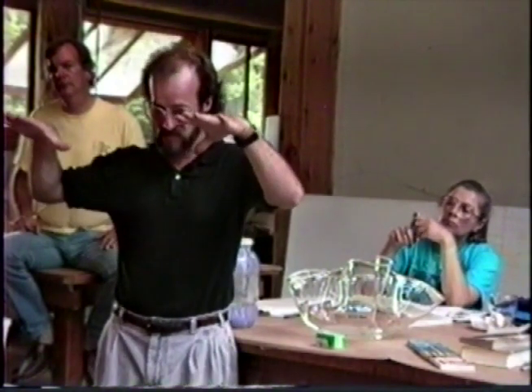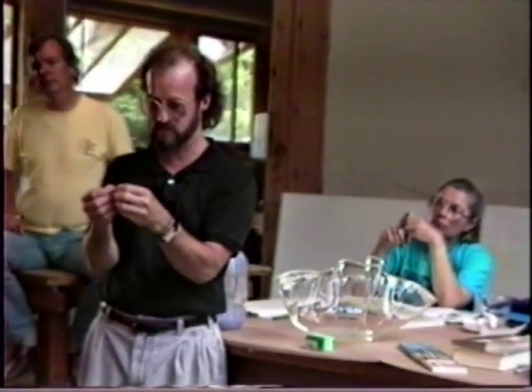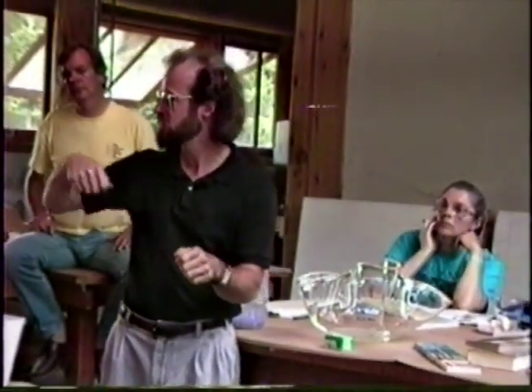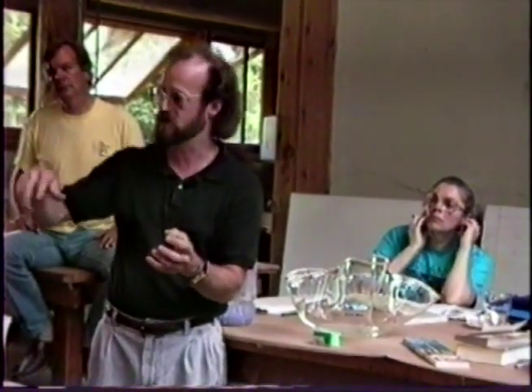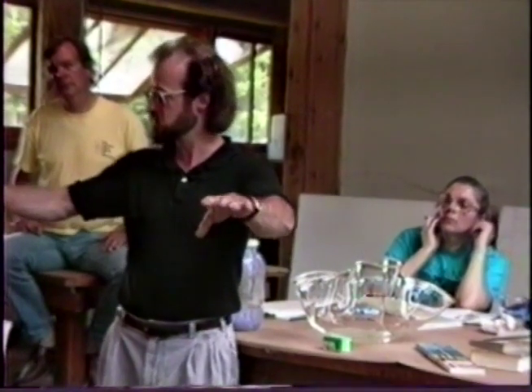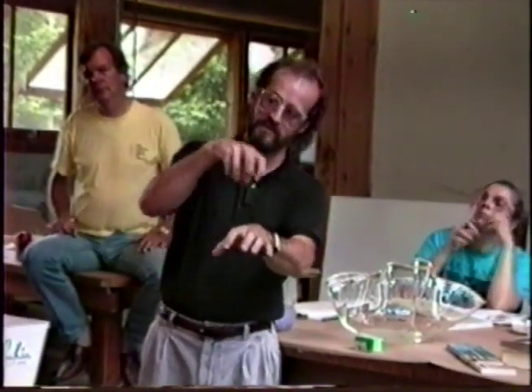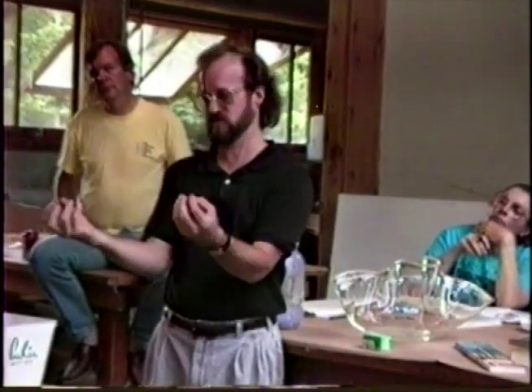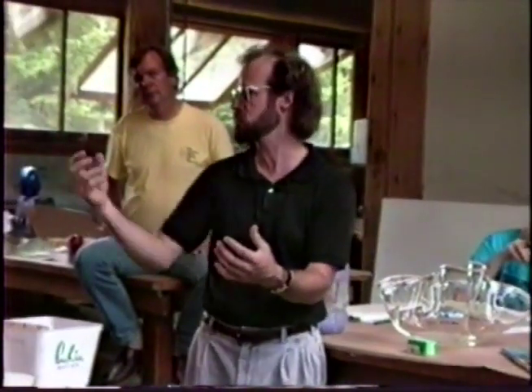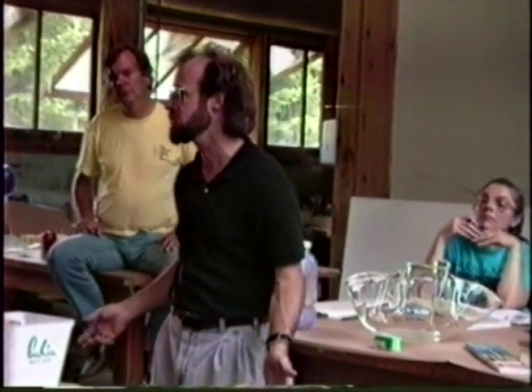Now that piece of glass had sealed down against the kiln shelf and trapped air in there. So as soon as it started thinning out, the air just went right up through it and blew a bubble about that high. Then that became a technique for me because I go in there and pop them. And then I figured out how I could make them happen where I wanted them by having a single layer of black, which was real soft, putting second layers around, and the spots that were single layers would blow bubbles almost exactly where I wanted them. So that became a technique in the whole series.